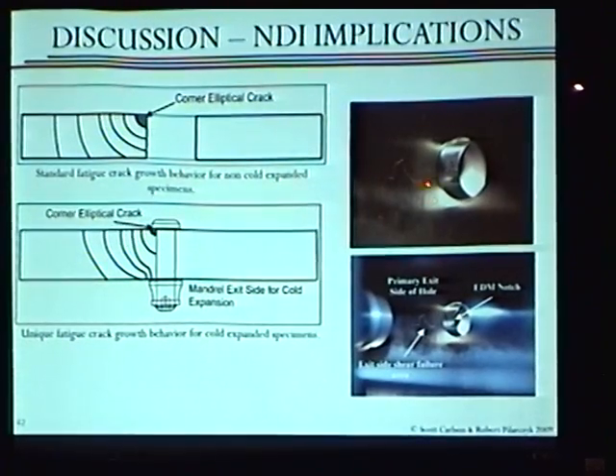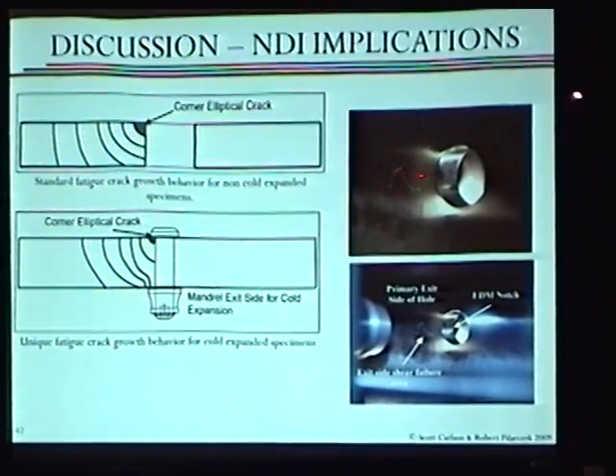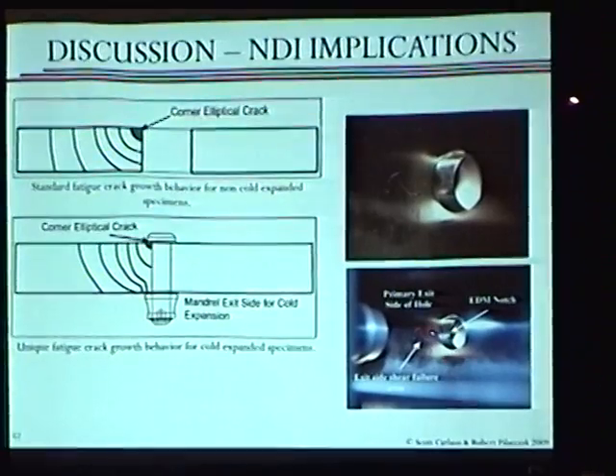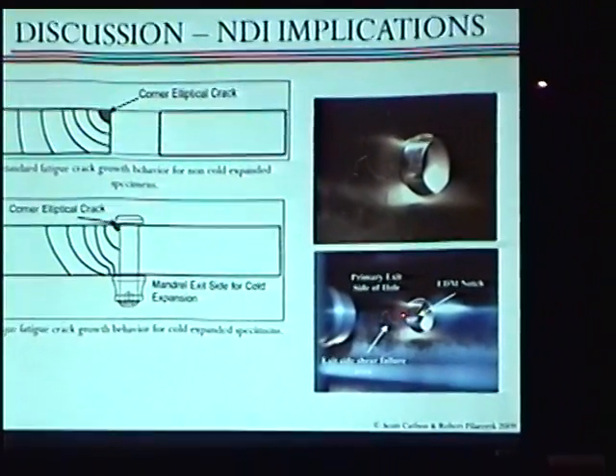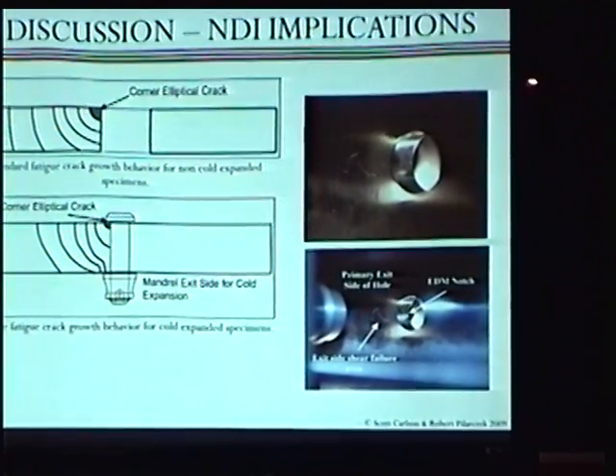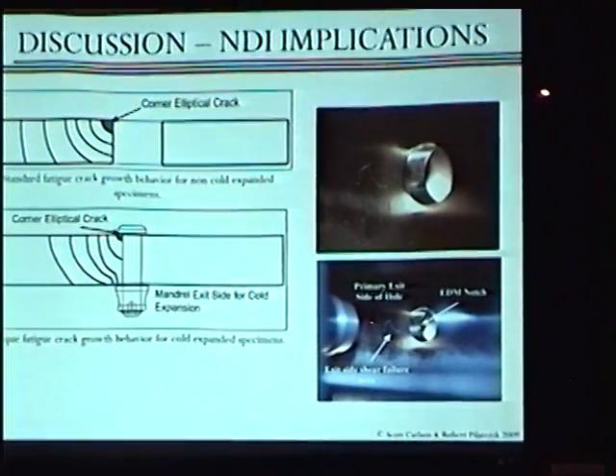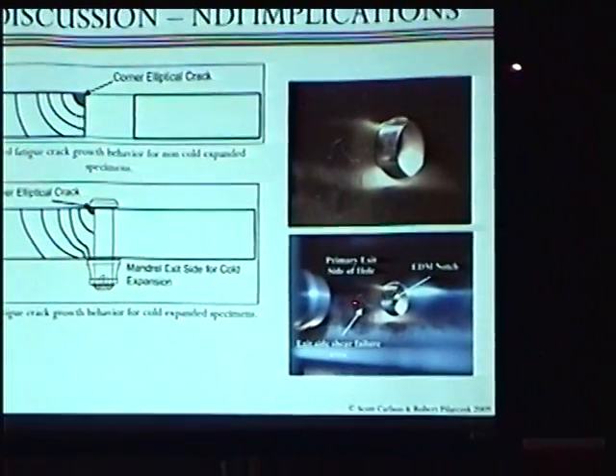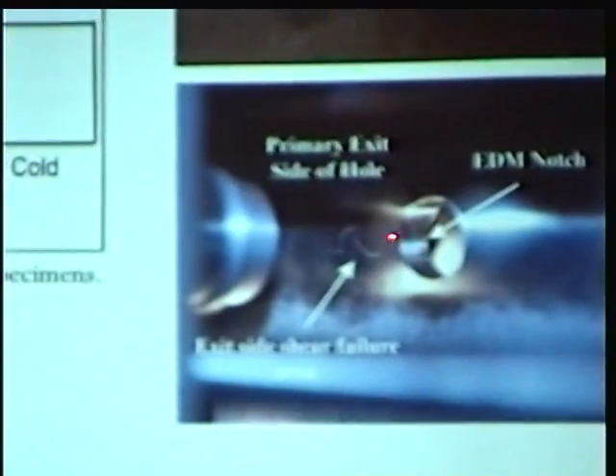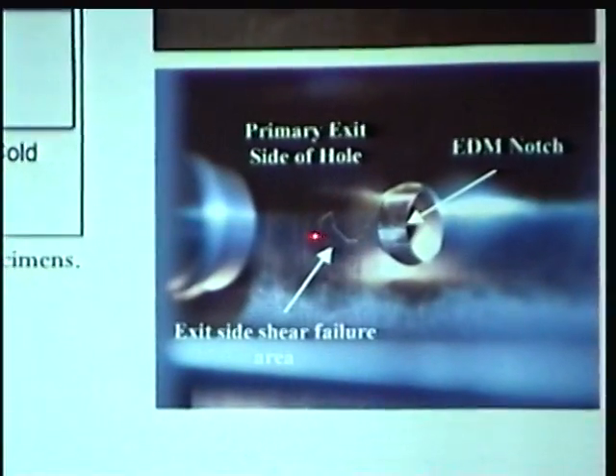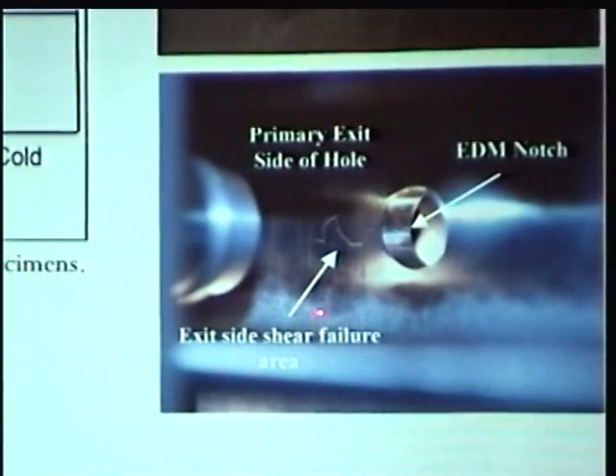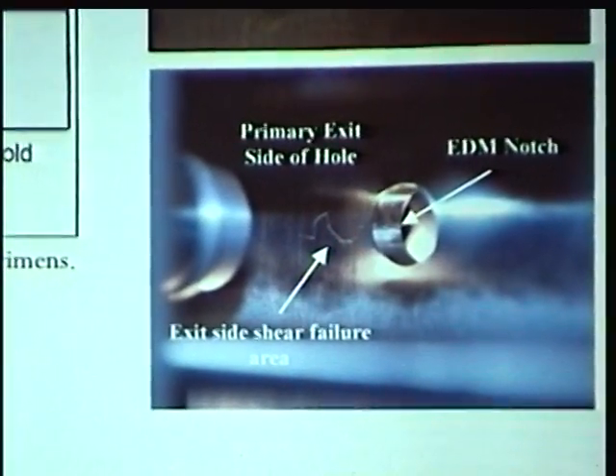So these are some of the pictures, some of the crazy cracks we saw in our testing. What really happened is we had about a 1/10 inch crack right here on this side. We're looking at the exit side. And then we had this crack growing out over here too. None of this was here. None of this was here. So we had this little teeny crack, and then it grew all the way around, and it was starting to grow out here. It was really crazy. And then all of a sudden, one cycle, this thing just popped.